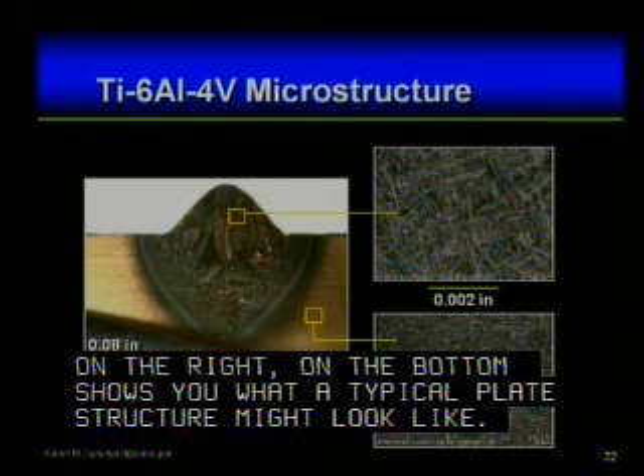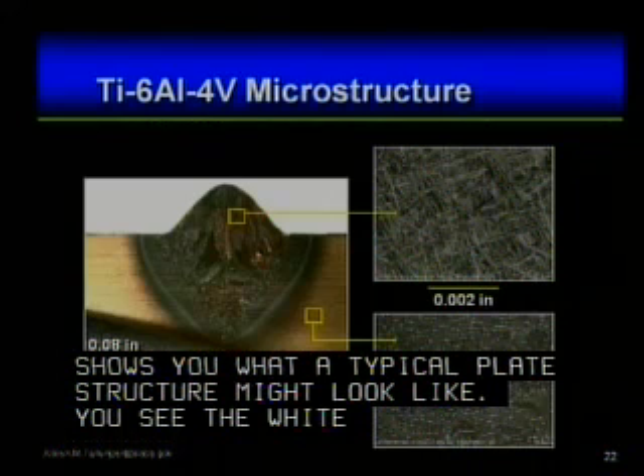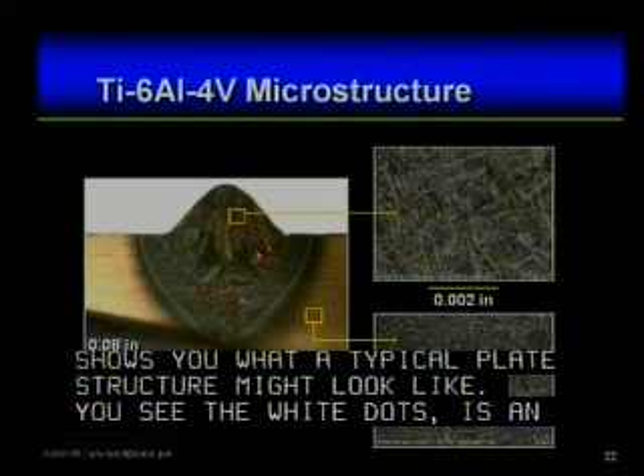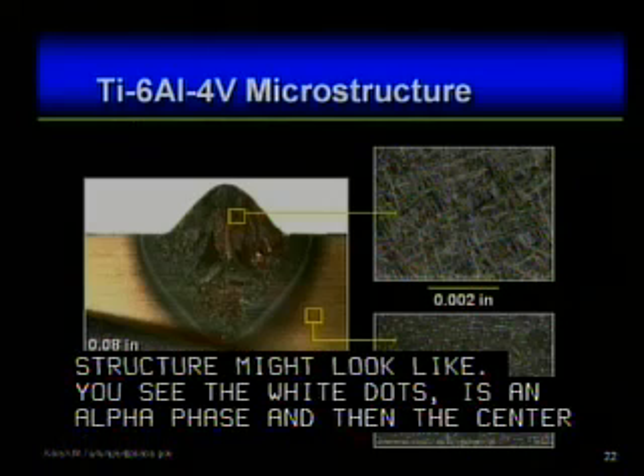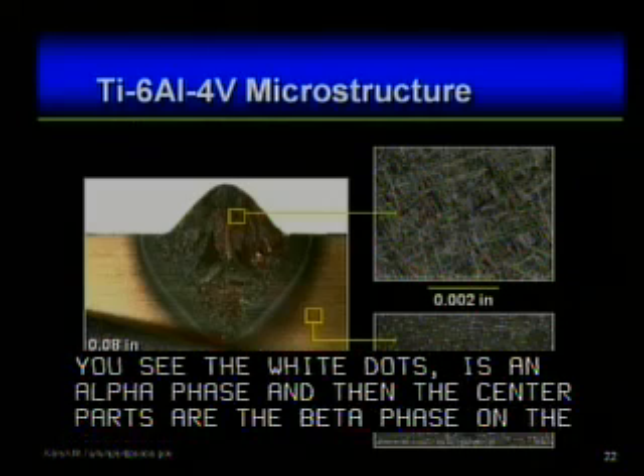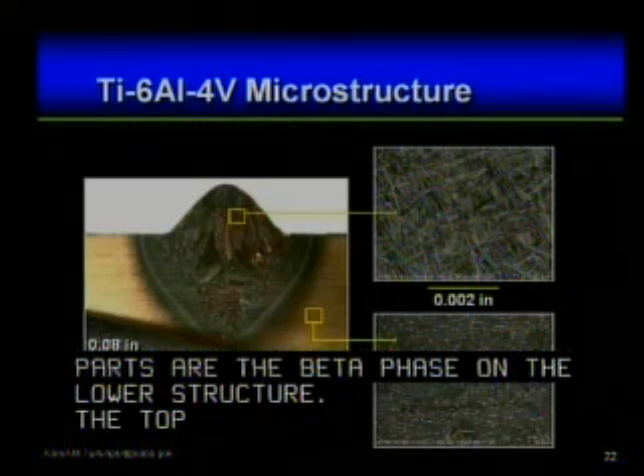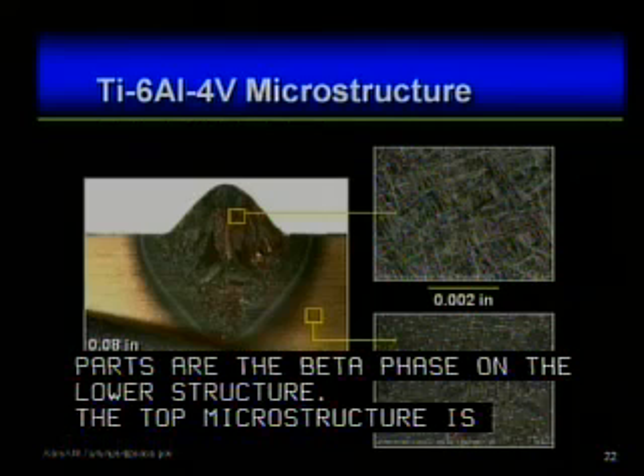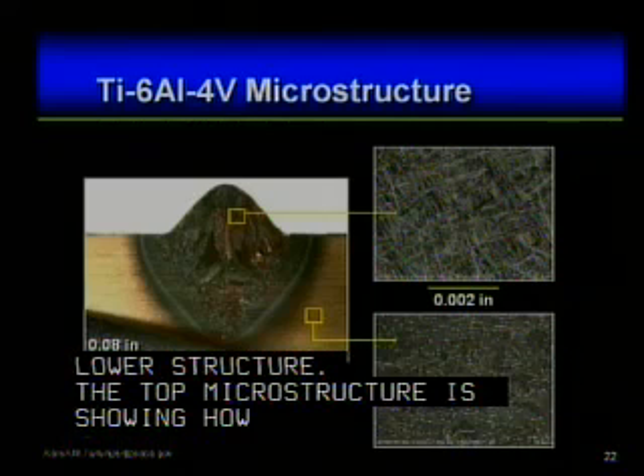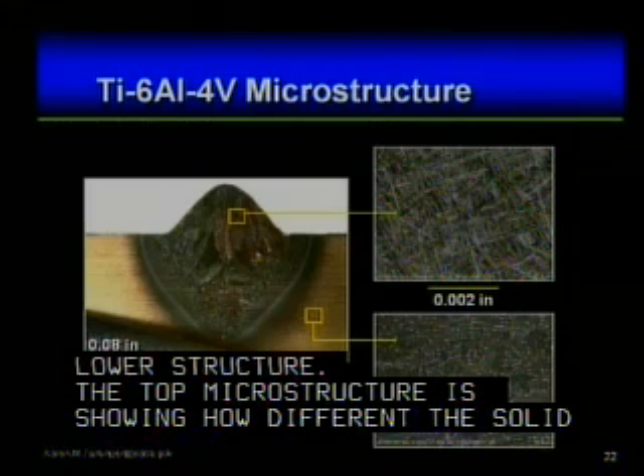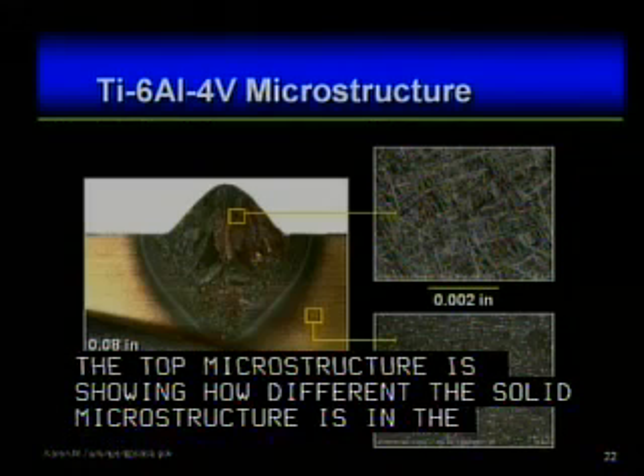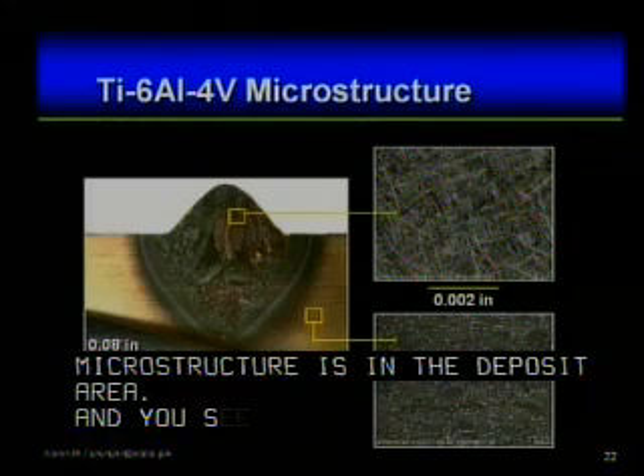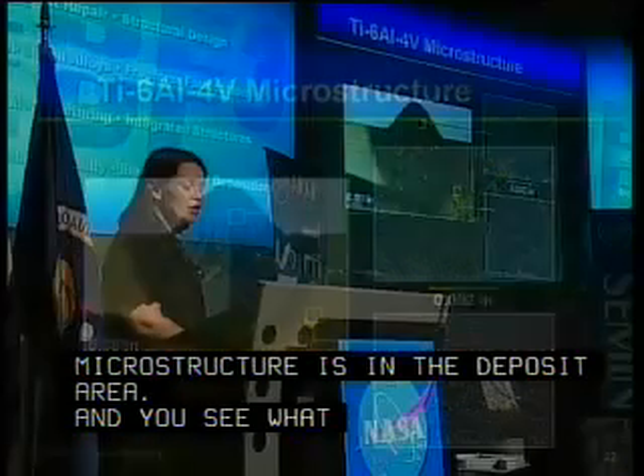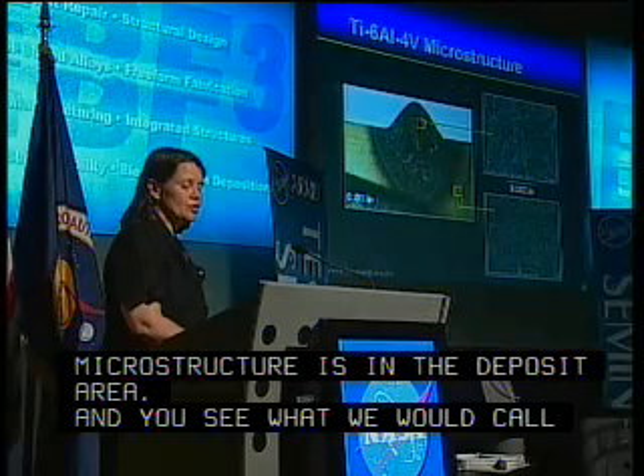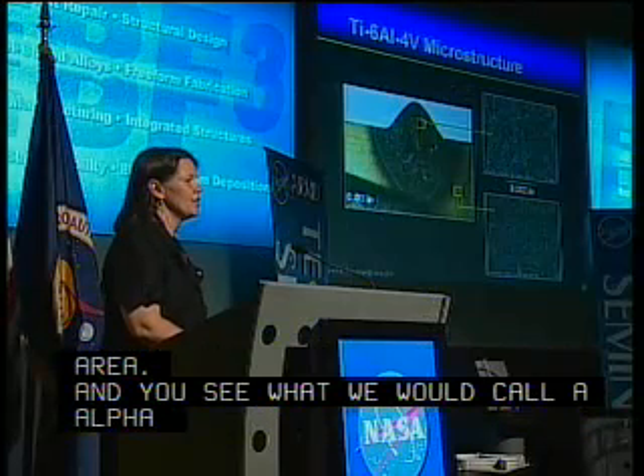You see the white dots, which are an alpha phase, and the center parts are the beta phase in the lower microstructure. The top microstructure shows how different the solidified microstructure is in the Ti-6-4 deposit area. You see what we would call a Widmanstätten alpha-beta lath structure. But again, heat treatment will bring that structure down to something that looks similar to what we have down below.